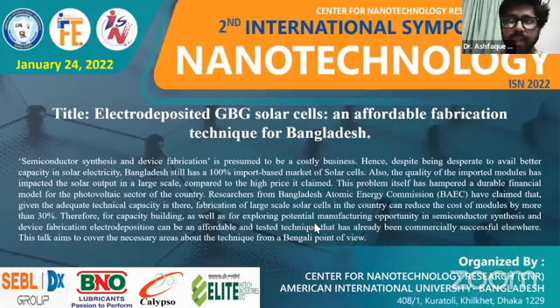devices. And the reproducibility is possible, but we have actually seen 18%, 18.5% efficiency as well, but we could not really reproduce those. So I agree that reproducibility can be a question, but there are many parameters that need to be very carefully maintained and managed in order to keep the reproducibility at a level so that it can be used commercially.